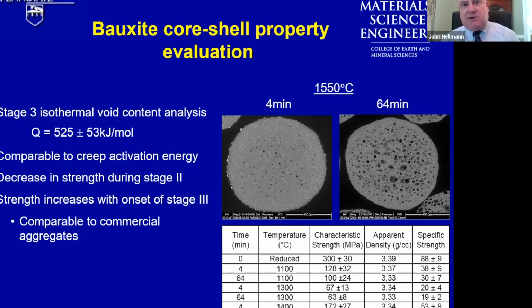We studied the kinetics of that process and found that the activation energy of the pore evolution was on the order of 500 kilojoules per mole, which is comparable to the creep activation energy of aluminosilicates of this composition. This is an interesting result because it supported our hypothesis that the evolution of this porosity in an already dense ceramic was the result of evolution of oxygen, blowing bubbles, if you will, in the interior of the ceramic particle when you process the material in a controlled oxygen partial pressure.